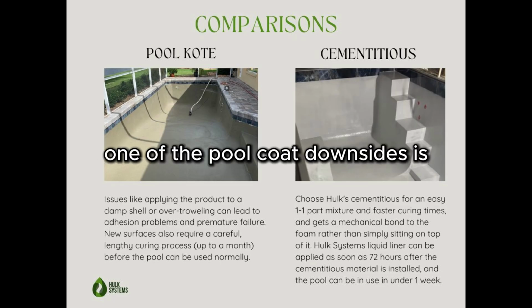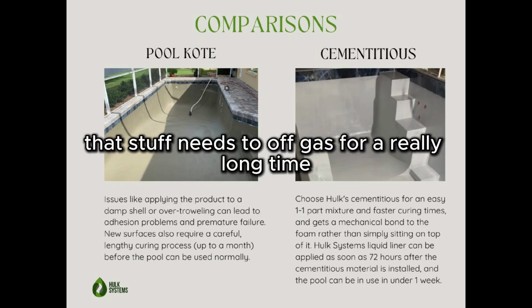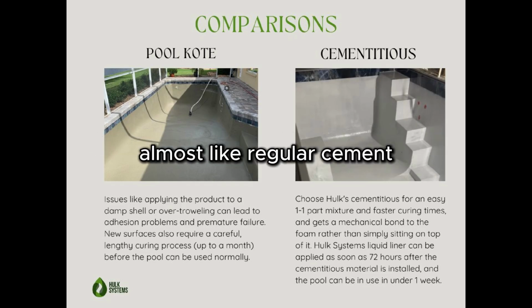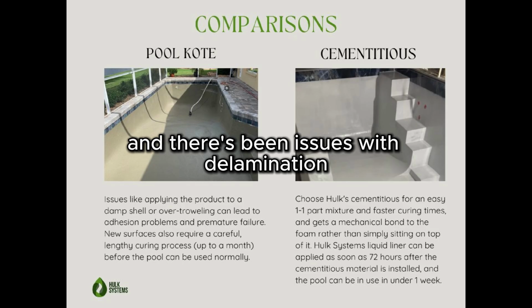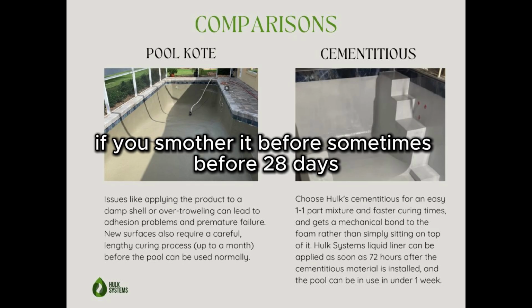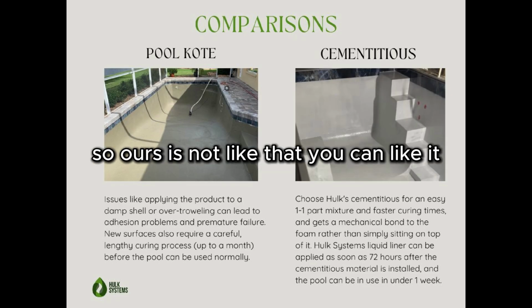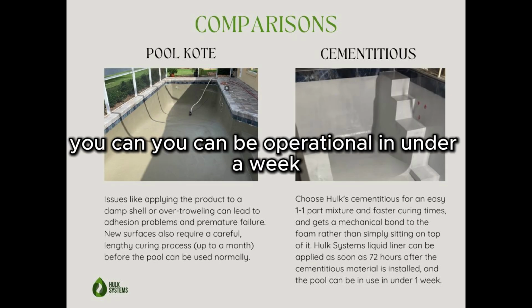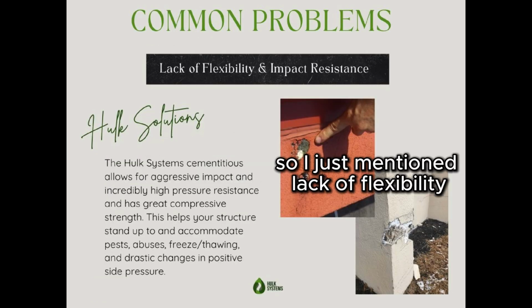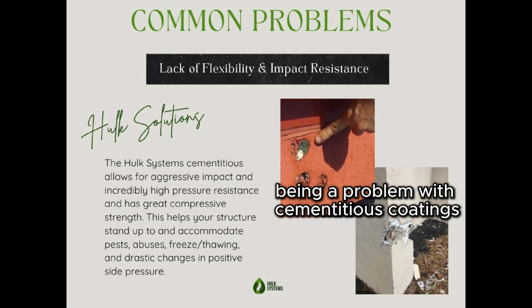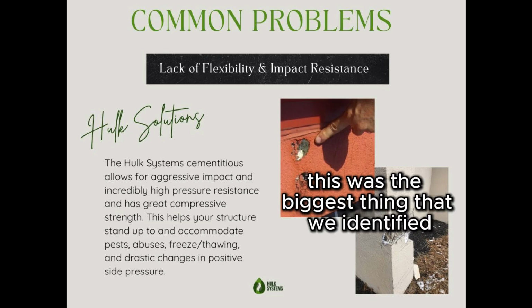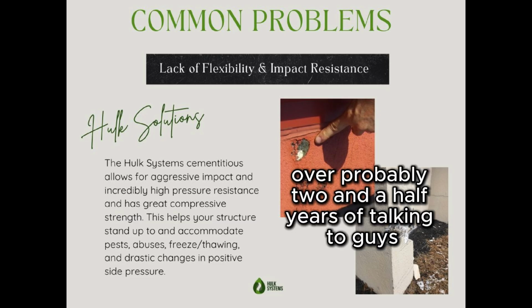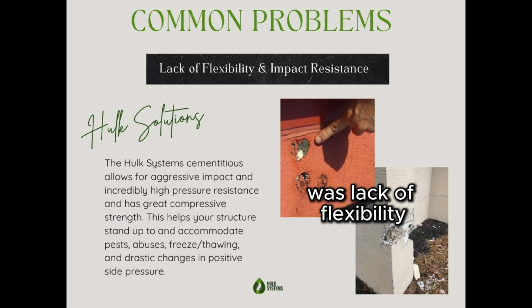One of the pool coat downsides is that stuff needs to off gas for a really long time, almost like regular cement. And there's been issues with delamination if you smother it sometimes before 28 days. So ours is not like that. You can line it. You can be operational in under a week. So I just mentioned lack of flexibility being a problem with cementitious coatings. This was the biggest thing that we identified over probably 2.5 years of talking to guys using different pool products, was lack of flexibility.